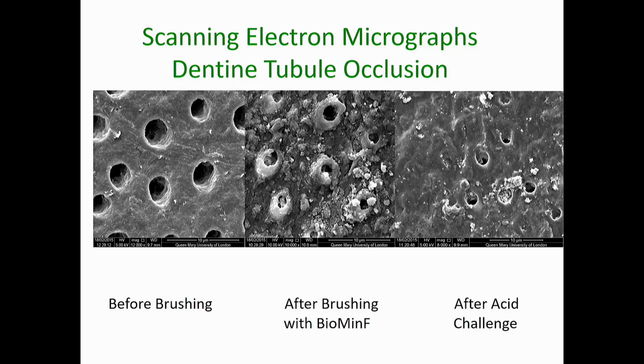Here we have the scanning electron micrographs of dentine before treatment with the toothpaste, on the extreme left, and you can see the dentinal tubules here. For example, here's one of the dentinal tubules, here's another. Then the middle micrograph is after brushing with Biomin F toothpaste and immersion in an artificial saliva. You can see that the tubule diameter has decreased quite markedly. And you can also see, if you look carefully, some little glass particles still sticking to the surface of the dentine.